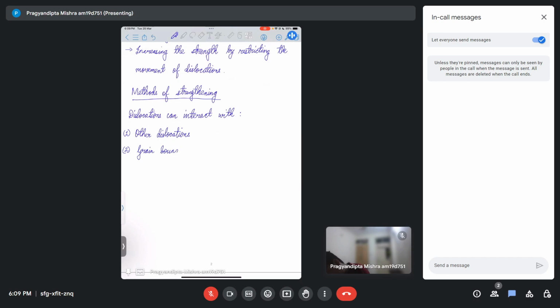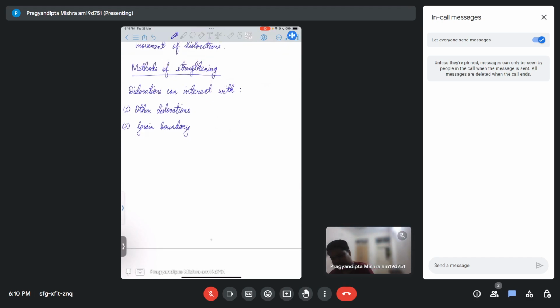Again, we have talked about how there are grain boundaries within the material system, which are formed when grains of different orientations form simultaneously, so that there will be a boundary between two grains which are at different orientations. Now this grain boundary can also act as a source or sink for dislocations. When that happens, the dislocation motion is restricted, and sometimes even completely stopped because of the grain boundary. So the grain boundary can also influence the dislocation motion.